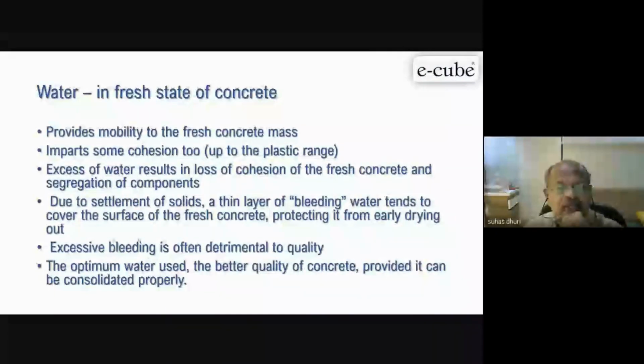Excess water is creating bleeding, basically. Optimum water content also gives very good cohesion. If you have excess water, you'll find that the bigger aggregate particles are going away from the concrete. It's called segregation. So when you place such concrete in the structural member, what is happening is you get aggregate at one location and cement paste at another location.